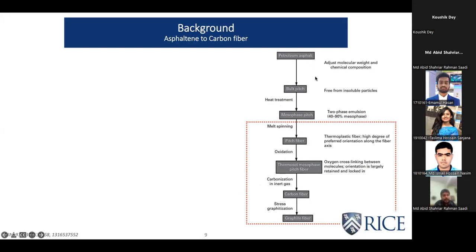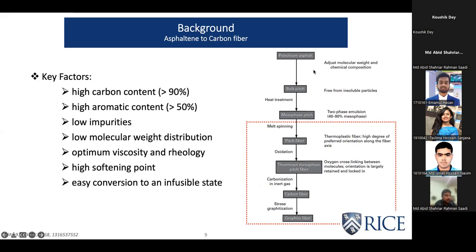So the pre-treatment strategy is very important, and one of our goals in this project was to determine and optimize the pre-treatment strategy for asphaltenes. And regarding the mesophase pitch, which is also a newly introduced term, I will explain in detail soon. So for the pre-treatment strategies, I have noted down some of the important factors that need to be taken care of when you develop and optimize them. Basically, your precursor needs to have very high carbon content, high aromatic content, low impurities, and a low molecular weight distribution.